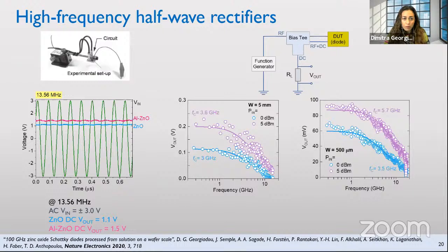zinc oxide diode. Now, to be able to see what happens if we move to higher frequency, higher than 13.56, we had to change a bit the setup and use this setup here. And this comprises a bias T, the diode under test, and the load resistor to measure the output voltage, and a function generator that can go up to 20 gigahertz. And in that case, again, we see that the cutoff frequency we get for the larger device is above 3 gigahertz. The smallest device, as expected, shows an even higher performance, which goes up to 5.7 gigahertz.